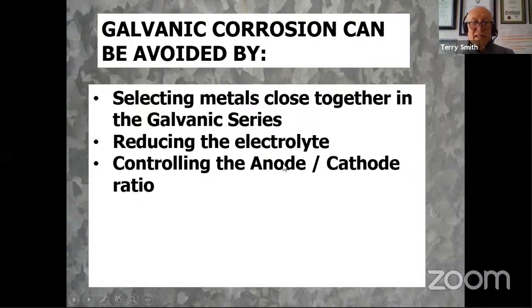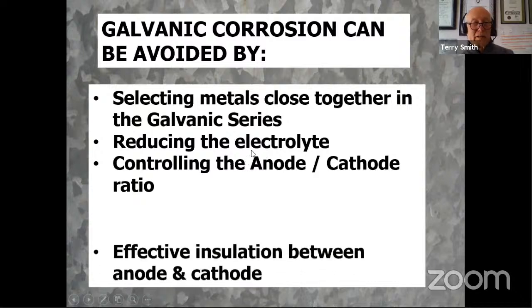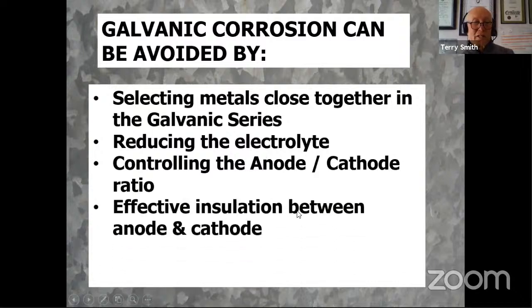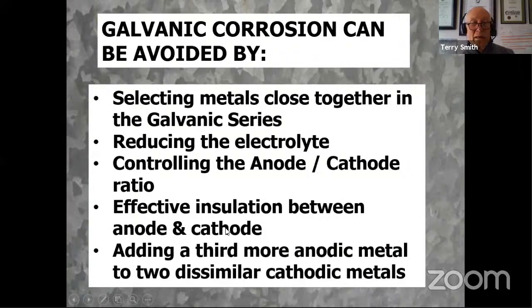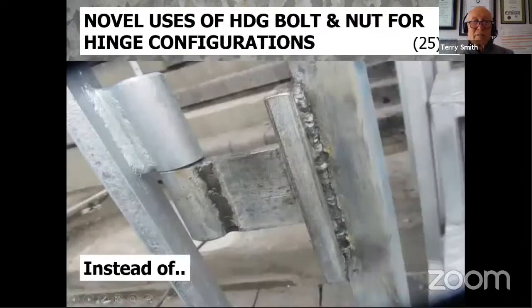For instance, the stainless steel roof, which is a big cathode with small anodes, would be a disaster, but the other way around with a zinc-coated roof and stainless steel screws will be a good idea. Use effective insulation between the anode and cathode, as you saw in the previous example, and then add a third anodic metal to 2 dissimilar cathodic metals, using zinc where you have brass and steel together, possibly.